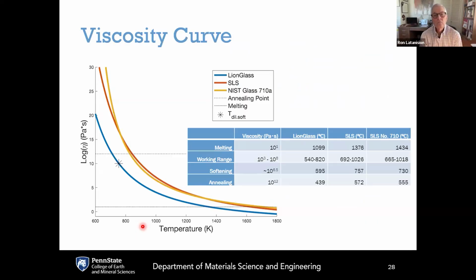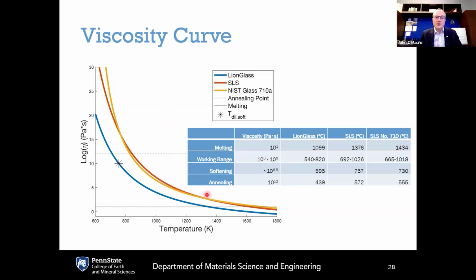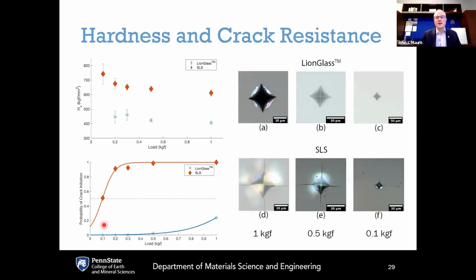One of the primary ways that this works is by lowering the viscosity curve. The red and the orange here show a couple of soda lime viscosity curves. This is the logarithm of viscosity versus temperature. And in blue, this is Lion Glass. You can see that the entire curve is shifted over to the left by quite a bit. Every part of industrial glass manufacturing is not really controlled by temperature. It's controlled by viscosity, by how fast the molten glass is flowing. Every stage is controlled by the glass flowing at a particular rate. So in moving from soda lime to Lion Glass, what we want to do is maintain the same viscosities that are used now, but shift the temperatures lower in order to match the same viscosities.